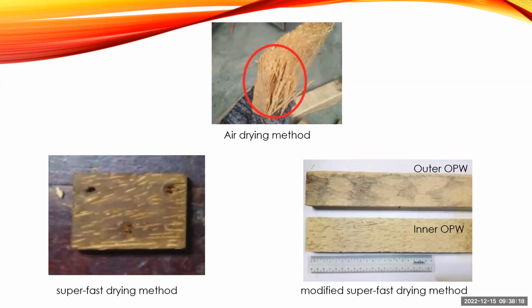But for the super fast drying method, like we mentioned before, it required holing on the oil palm lumber before it was dried. We can see the holes here, and this inhibits it from being used effectively in the lamination process. But for the modified super fast drying method, there are no holes in the drying process, so we can see there are no visible defects on the dried samples.